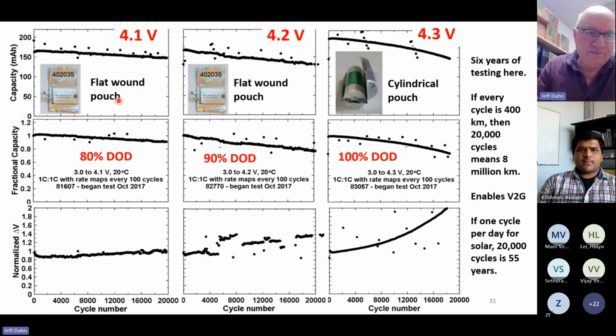And when they're put into lithium-ion cells and operated at 80% depth of discharge or 90% depth of discharge or 100% depth of discharge over 20,000 cycles, 6 years of testing, there's very little capacity loss. And these particular cells would drive a car 8 million kilometers. This would enable vehicle to grid without any issue at all. So these are batteries that won't wear out. And they can be made today. Single crystal positive electrode materials are becoming very popular in China. Lots of lithium-ion cells use them.